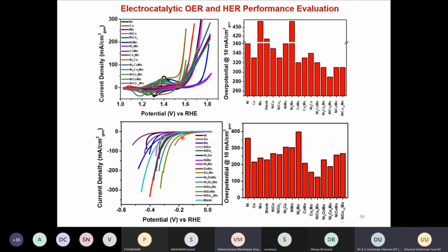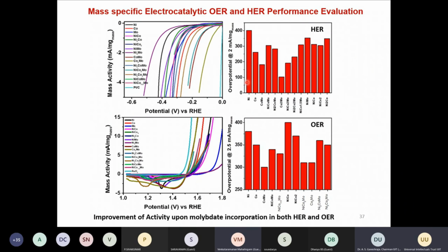So here also you can see that nickel, cobalt 2 and molybdenum shows better activity compared to other materials. We also did the mass specific activity, and what we found is that on a mass specific activity basis, the cobalt molybdenum shows a better activity compared to the nickel cobalt molybdenum sample. But still, if we consider the geometric activity, NiCo2Mo shows a better catalytic activity.